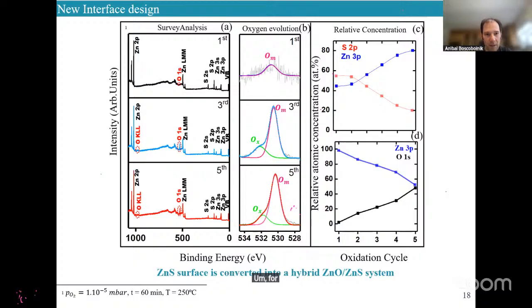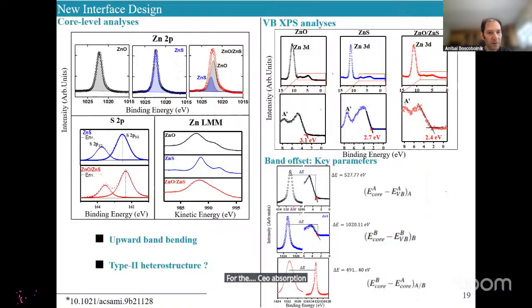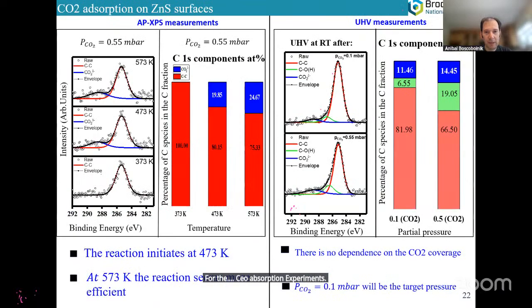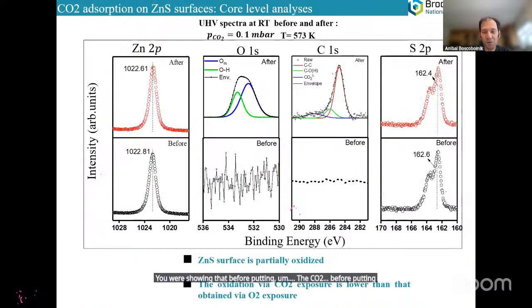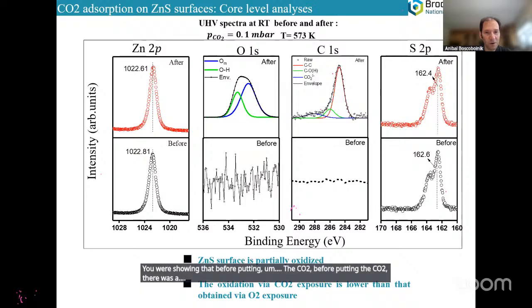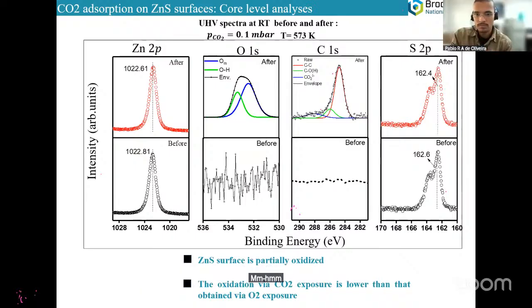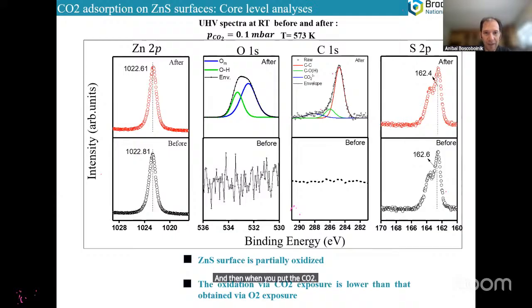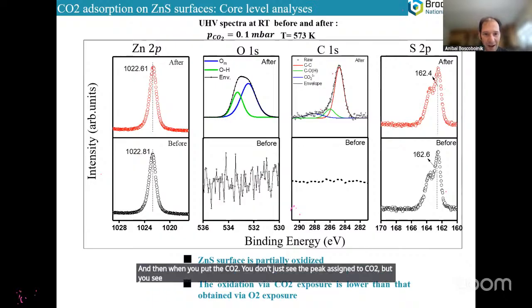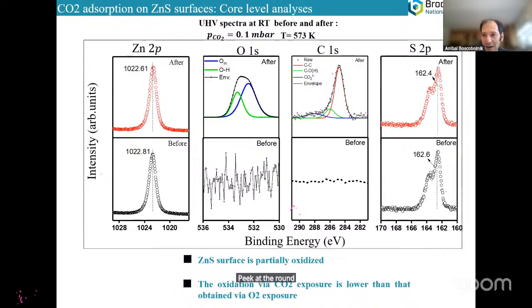For the CO2 adsorption experiments, you were showing that before putting the CO2, there was no carbon. And then when you put the CO2, you don't just see the peak assigned to CO2, but you see this other peak at around 285, aliphatic carbon. Where is that coming from? Because it wasn't there before.